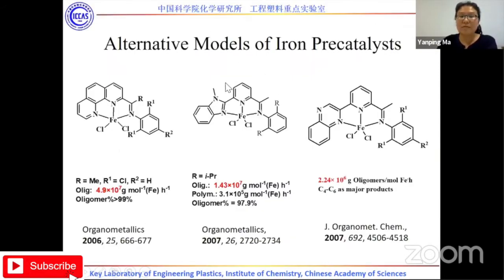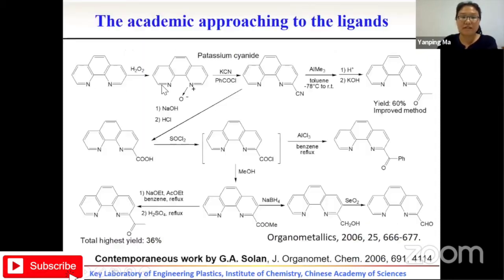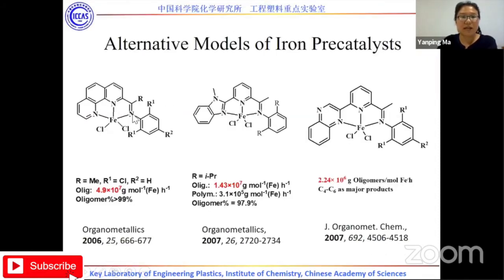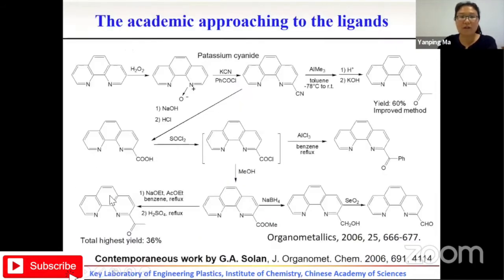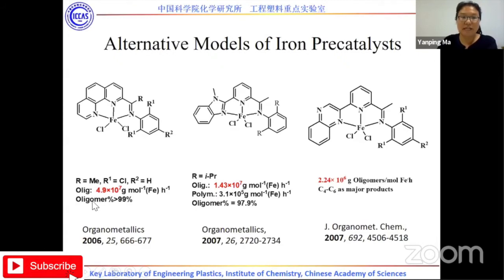We also developed the catalyst with conjugated pyridine ligands. By this catalyst, the activity is high, but the products have low molecular weight. They are oligomers. Even though it is unexpected, the oligomers are good. We can see 99%. We can get good results here.